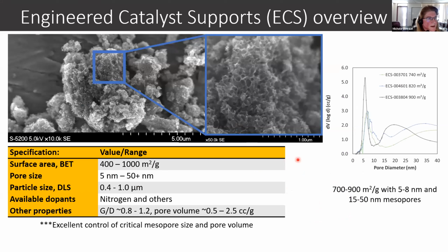So I'm going to spend a couple of minutes just talking about our engineered catalyst supports, because these are very, very important materials for both the fuel cell as well as the electrolyzer type applications. Here we've developed capabilities to produce these carbon supports with very, very high surface areas, which you can imagine is going to be ideal in these situations. And then also very controlled pore sizes from 5 nanometers to 50 plus nanometers. And on the right-hand side, you can see we've actually engineered mesoporous structures as well. So we've got a combined pore size of around 5 to 8 nanometers, and then also 15 to 50 nanometers. And so these characteristics of our supports are very, very important to give our catalyst materials their best functionality.